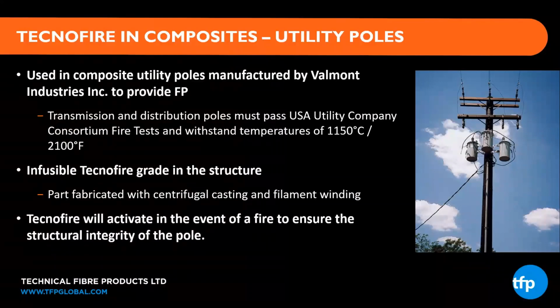I'm sure everyone is aware from the news of the increased frequency of wildfires around the world. Classical wooden power or utility poles are easily destroyed during a wildfire, leading to power outages and significant expense in re-establishing the network. Valmont in America have developed a composite utility pole which passes the USA Utility Company Consortium fire tests, which mimic exposure to a wildfire with temperatures of 2,100 degrees Fahrenheit. The poles are made using filament winding or centrifugal casting, incorporating an infusible grade of Technofire during construction. And the Technofire intumescent veil activates and expands during a fire to protect and insulate the backing laminate and ensure the structural integrity of the pole is maintained.